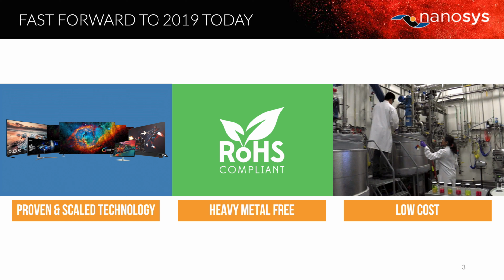So what does that look like in terms of the industry? Well, obviously, progress has allowed for massive proliferation in displays from 7 inches all the way up to 98-inch displays. We've seen the implementations go from requiring high WVTR barrier films and glass to a lot of other types of packaging formats. Now we have on-chip implementations using quantum dots, and on-glass thin films using quantum dots. For example, the HP Pavilion 27 product shown here uses a 10 micron thin QD film on a Corning Iris glass light guide plate, which enables the overall desktop monitor to be thinner at 27 inches than your iPhone, which is really a phenomenal form factor advantage.